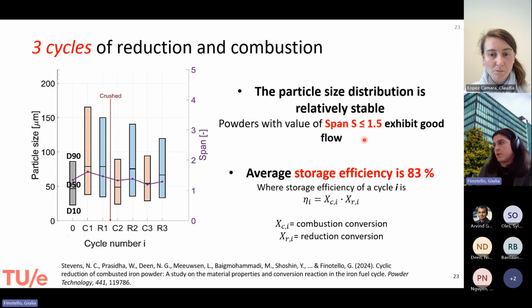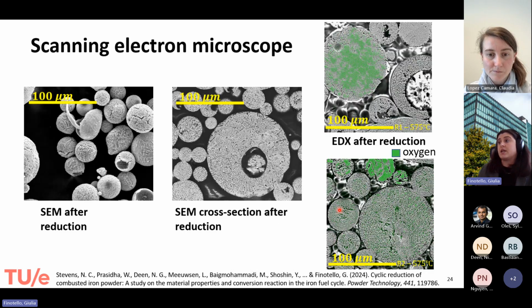And then what we also saw is that we had an average storage efficiency of 83%. And this was really the first trial, the first 3 cycles that we did. Here you can also see some SEM images and even the cross section, where you can see the porous structure of the reduced powder. However, we've seen that we couldn't reduce fully. There was still some oxygen in some particles, while others were fully reduced.